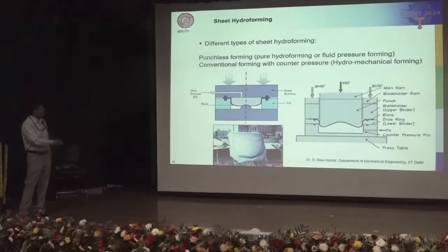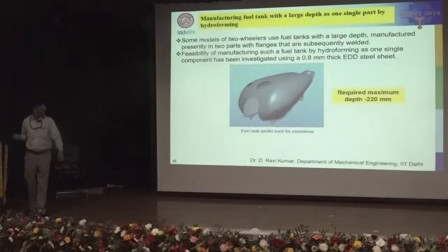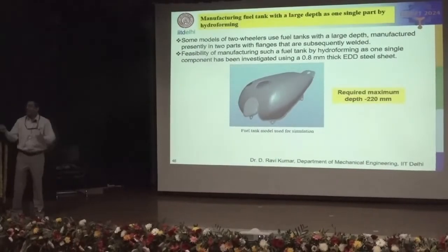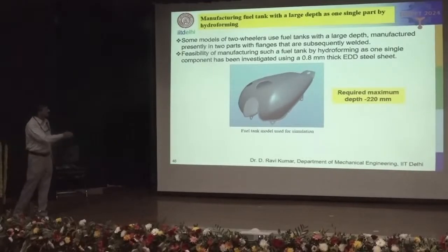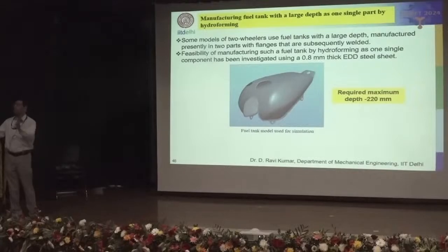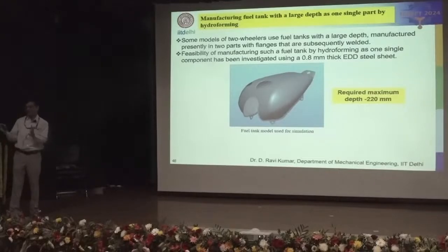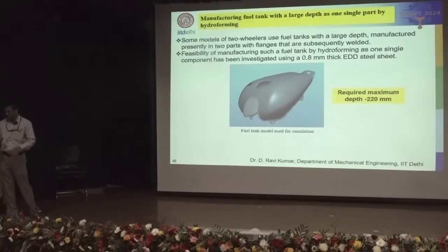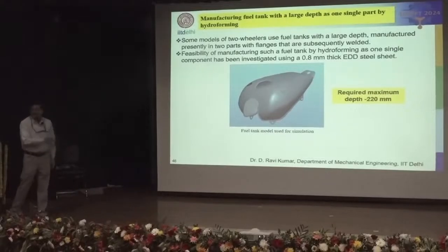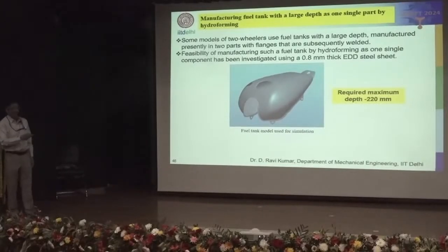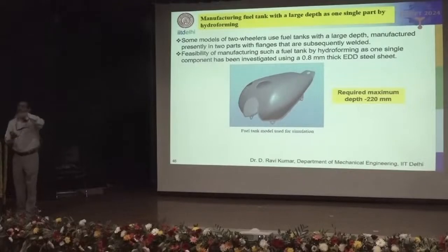So lastly, I just want to show one more small case study. I'm going back to the same fuel tank again. Now we have considered a fuel tank with much larger depth. In bikes you get more intricately designed fuel tanks, and some of the fuel tanks have very large depth. This particular model has 220 mm depth. We have done simulations to see whether this fuel tank with large depth can be manufactured as one single component by hydroforming, which is not possible by conventional forming.